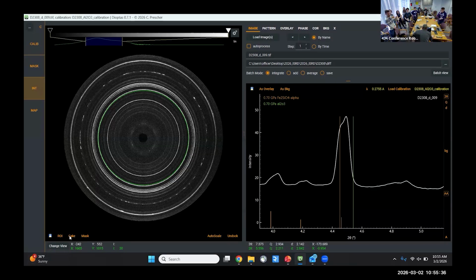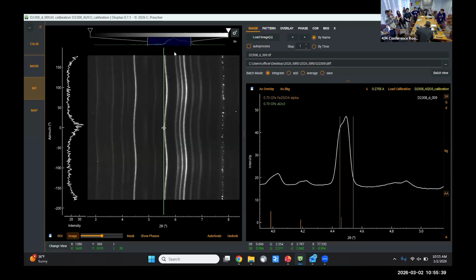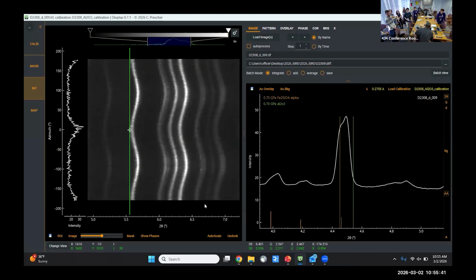So if we look at that cake plot now we see that this is 90 degrees. They're reflecting by a larger amount of two theta. And less so. So basically to fit the ellipse, we do it in this geometry, and you just fit this peak along this whole thing. And then from that, you'll know the pressure and the differential stress of your material. And you also know the strain, so you can generate stress strain curves.